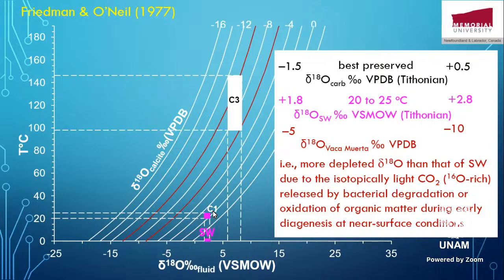Then here comes the problem where the C1 was, which is the lime mud. Well, we can see here that the best preserved carbonates, if you get it from Veizer et al. 1999, is between +0.5 and -1.5. But if we take those values and apply them to a curve similar to this to predict the delta O18 of the seawater, at 20, 25 degrees, this should give seawater between, say, +2.8 and 1.8. So we're talking about 2 and 3 generally.